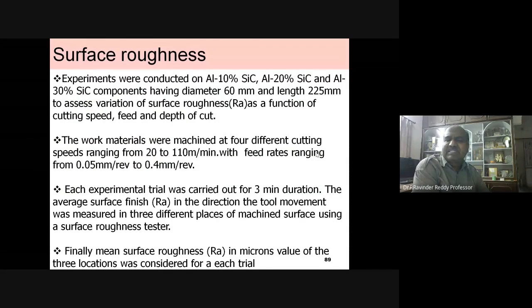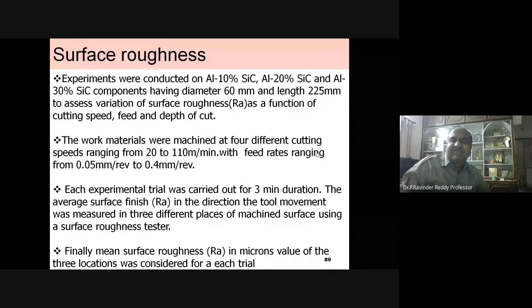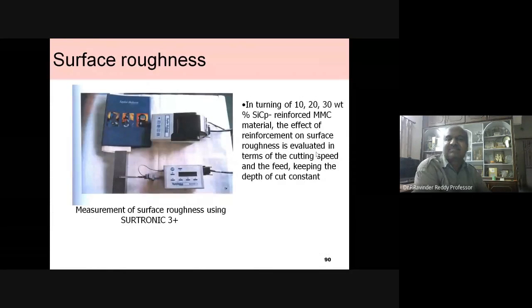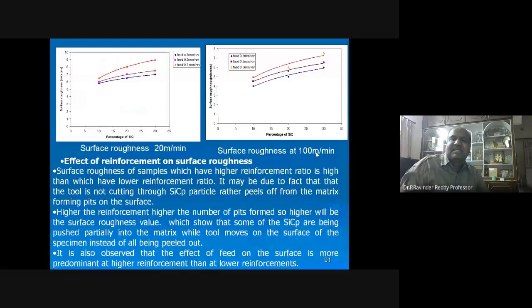The work materials were machined at 4 different cutting speeds ranging from 20 to 110 meter per minute with feed rates ranging from 0.05 mm per revolution to 0.4 mm per revolution. Each experimental trial was carried out for 3 minutes duration. The average surface finish in the direction of the tool movement was measured in 3 different places of the machined surface using a surface roughness tester. Finally, mean surface roughness in microns of the 3 locations was considered for each case. This is the surface roughness measured using Surtronic for turning of 10, 20, 30%, as I mentioned.